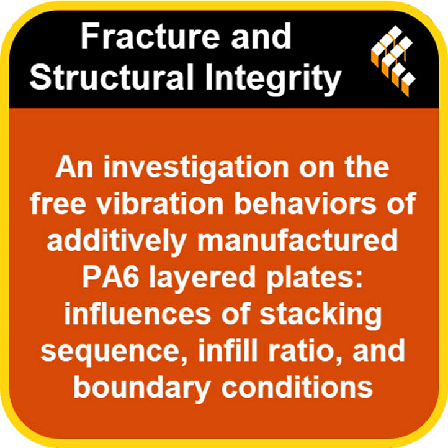Like, ballpark. Well, let's take that simplest configuration, the 40-40-40 plate with an aspect ratio of 1, so it's a square plate. Its first natural frequency under fully clamped conditions was around 80 hertz. But under simply supported conditions, it was only about 44 hertz. Wow. That's nearly double the frequency just by changing how the part is mounted or constrained. It is. Those clamped edges provide much greater resistance to movement and flexing, making the whole structure effectively much stiffer.